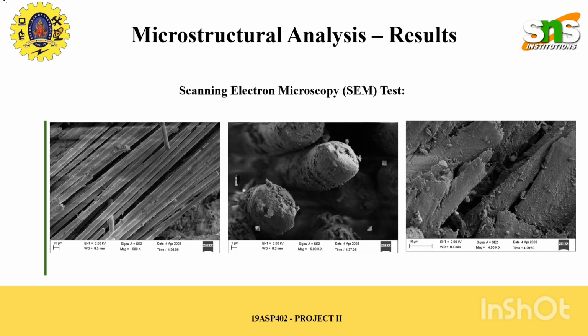Further microstructural observations using SEM show the fracture behavior of the composite. The images indicate fiber breakage and matrix cracking as the primary modes of failure. These observations confirm that the material is capable of handling stress effectively before failure, demonstrating reliable structural performance.